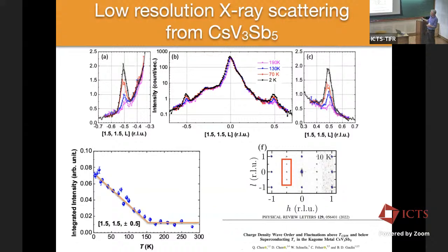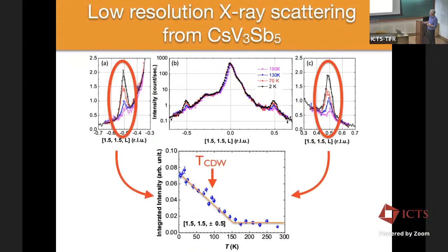So actually what you see on either side here is just a blow up of this region over here, so it's showing you the part of the signal that is temperature dependent. Everything else is temperature independent, and if we just focus on that, and we integrate up and fit the integrated intensity of these Bragg peaks as a function of temperature, this is the order parameter that we get right here. And anyway, so you can see right away that it's not what's seen in high resolution diffraction, and it's not what's seen in NMR and such, and that we see this very linear growth of the order parameter.